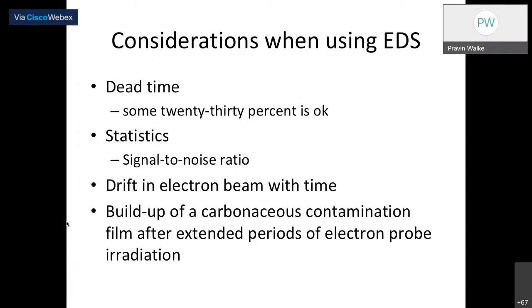Further one is the drift of the electron beam with time. If you consistently bombard the beam on a single spot, you will find there is a little movement of the electron beam. After a certain time, a drift of the electron beam can be observed on the surface. So the position cannot be the same if there is drift with time. So within a short span of time, if it is possible to get the signal from the X-ray, it will give you more ideal information about the specimen.